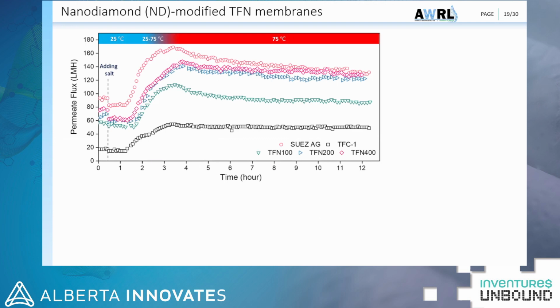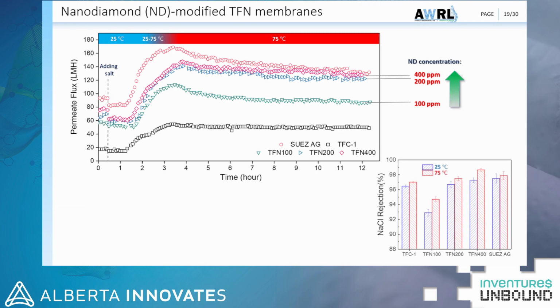The flux results show that by the addition of nanodiamonds, the flux increased and almost reached the commercial Suez membrane, with one big difference: the flux of our synthesized membrane was more stable at higher temperature than the commercial membrane. The salt rejection of the TFN membrane with maximum loading of the nanodiamond was more than the pristine RO membrane and commercial membrane. And again, it shows the successful incorporation of nanodiamond in the structure of the polymer.